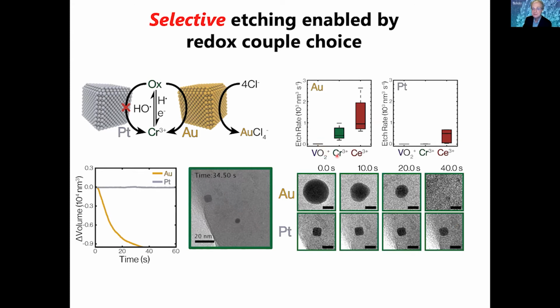What I think you can see here is that, for example, in order to be able to etch the platinum, we need to put the cerium, the highest oxidizing potential redox couple present. But if there's only chromium or vanadium oxide, there will be no etching of the platinum. If we're at the chromium case, again, the platinum is not etched, but the gold is. And if we go to the vanadium oxide case, then neither the gold nor the platinum is etched. So indeed, it looks like we can do that.